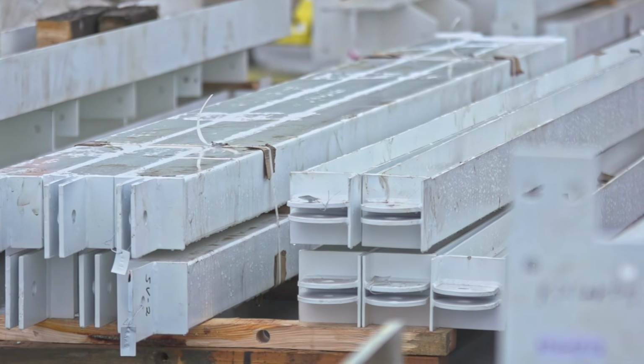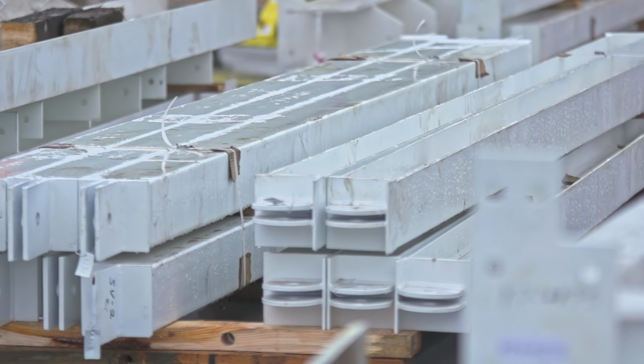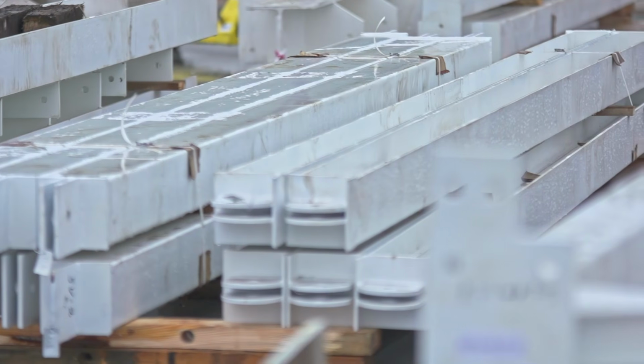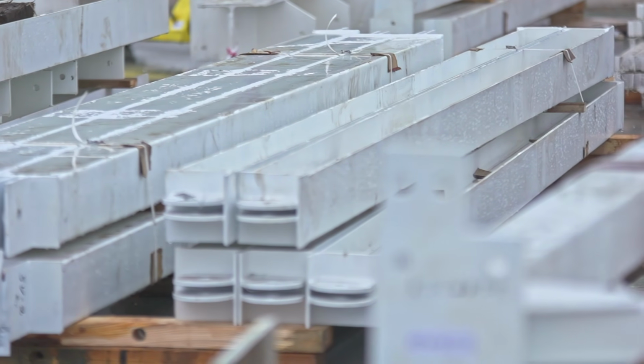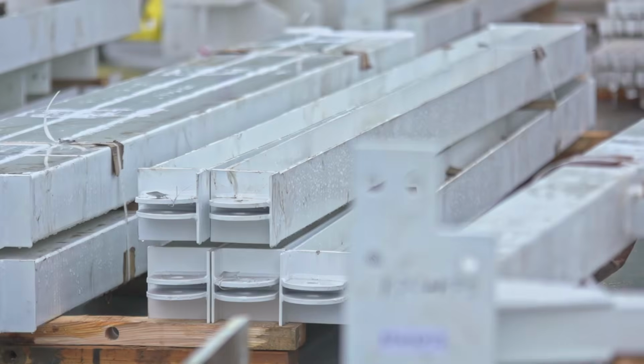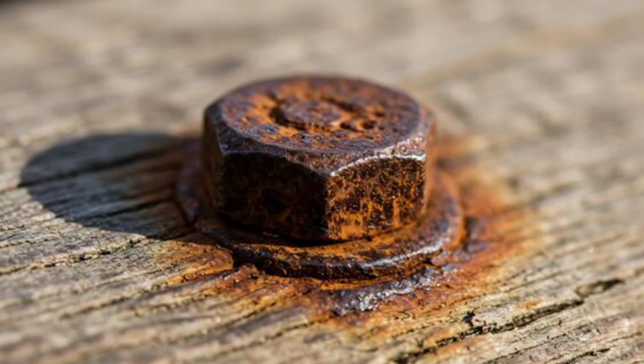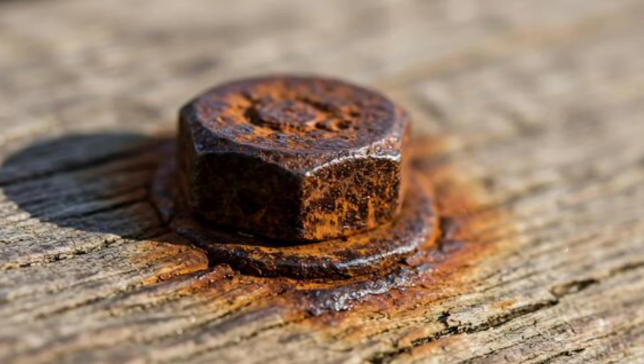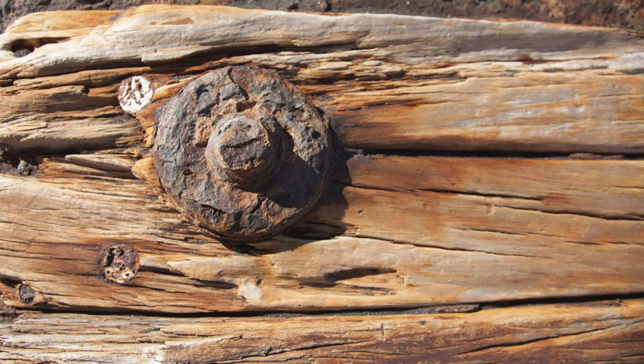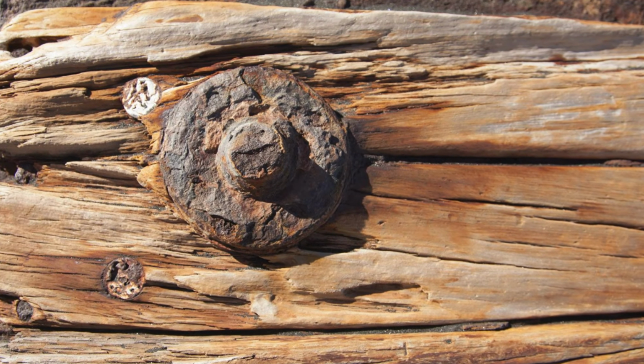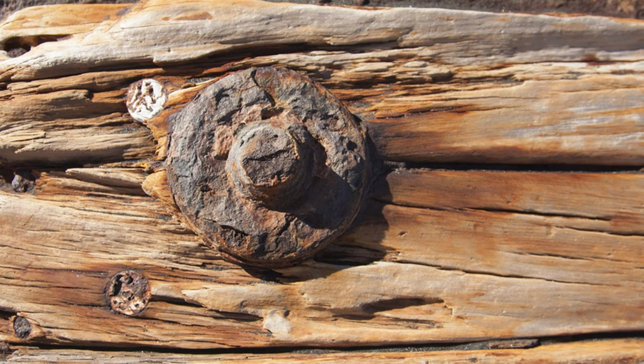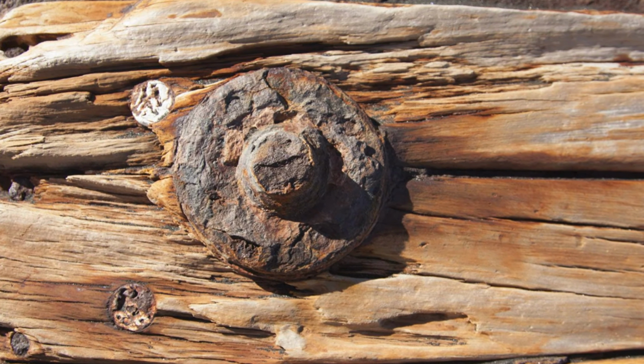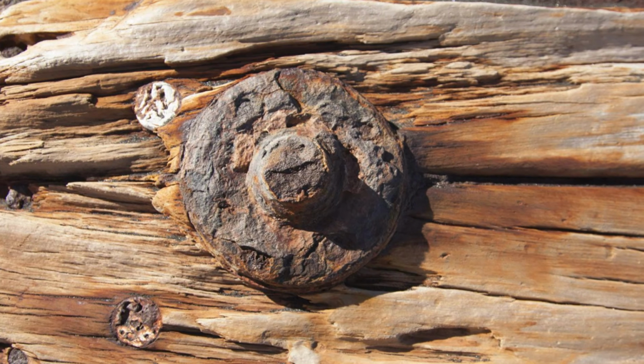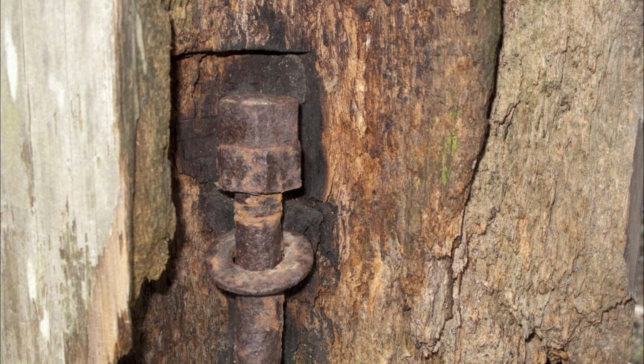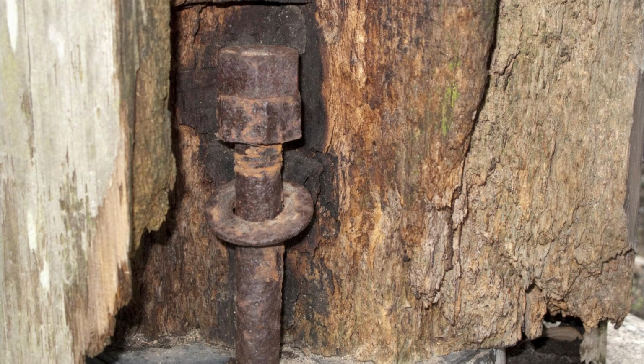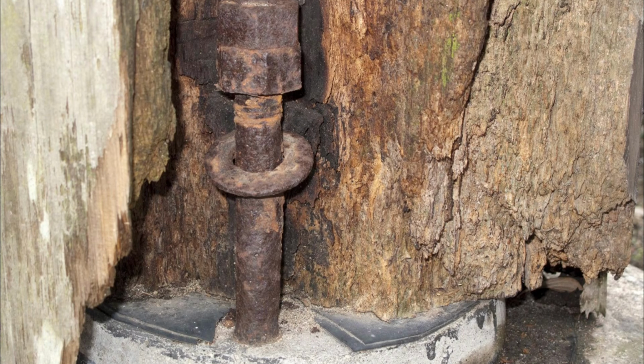Now, let me show you where iron enters the picture, because this is where the real lesson lives. When iron sits in saltwater, it corrodes. That's not a surprise to anyone. But what most woodworkers don't realize is what happens when an iron fastener corrodes inside a piece of wood. As iron rusts, it expands. Rust occupies roughly 6 to 10 times the volume of the original metal. So an iron bolt sitting inside a timber swells as it corrodes, and that swelling pressure cracks the surrounding wood from the inside out. You end up with what the old shipwrights called iron sickness, black stains bleeding out of every fastener hole, and timber that's splitting apart around bolts that have turned to powder.